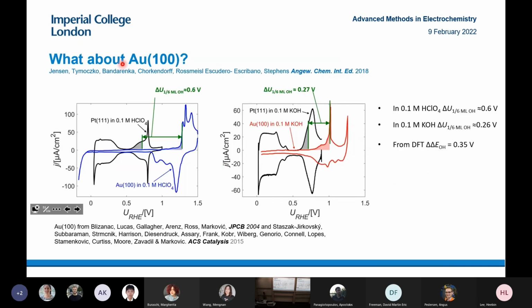Then we thought, okay, let's see what happens on other surfaces. As I mentioned previously, gold 100 is very active in alkaline media and less active in acid. So we had a look at the CVs, and what we found is that in acid, there's a destabilization of around 0.6 volts for the OH adsorption peak on gold 100 relative to platinum-111. But in alkaline media, there's only a destabilization of around 0.27 volts. So in alkaline media, it agrees better with the theoretical calculation. The theoretical DFT calculation suggests it should be about 0.35 volts destabilization. I don't know what's happening in acid, but it seems in acid you're somehow preventing OH from being adsorbed. I don't understand why that's the case.